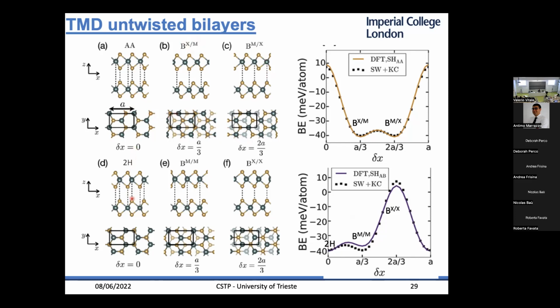But then I can also start from a different stacking, which is this 2H, where now the transition metal of the top layer is on top of the chalcogen of the bottom layer, and vice versa. So basically we have flipped the top layer before stacking, right? And you can create this Bernal stacking as well from these. And all these three belong to the same class. And if you twist, starting from any of these three, you get the same Moiré pattern, which is different from the other one. So these two are kind of topologically different. And in this class, the Bernal stackings are the ones with the lowest binding energy, so they are the favorable ones. Whereas in this class it is the 2H, which is the energetically most favorable stacking where the system needs to be in.